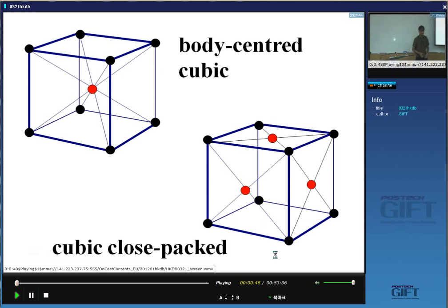Okay, so once again, we are looking at transformation between austenite, which has a face-centered cubic, but it's a closed-packed structure, so we often call it cubic closed-packed, into a body-centered cubic crystal structure. There's no difference in the allotropic transition. It's still going from face-centered cubic to body-centered cubic, but bainite forms at a higher temperature than martensite, so I explained to you that things get a little bit confused because it's possible for some atoms to be mobile at the higher temperatures.